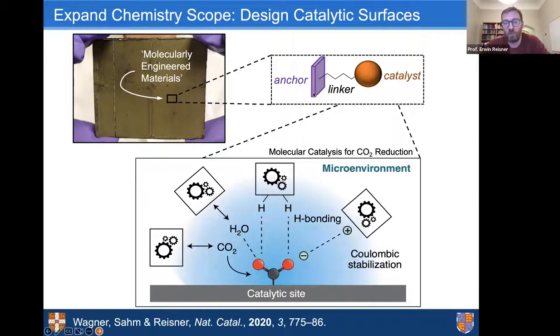So here you have two possibilities. Either you take, which is what we are doing, a molecular single site active site. Again, this can be just a synthetic catalyst, but it can also be an enzyme. And then you find a way to link and anchor this to your surface. Or alternatively, you have single site catalytic sites on a heterogeneous substrate, where you can really control substrate and product access and release, and importantly, stabilize intermediates, again to have selective and efficient catalytic reactions. And the microenvironment should not be underestimated. So we look into this quite closely at the moment.